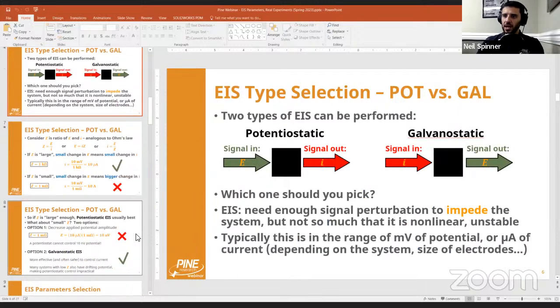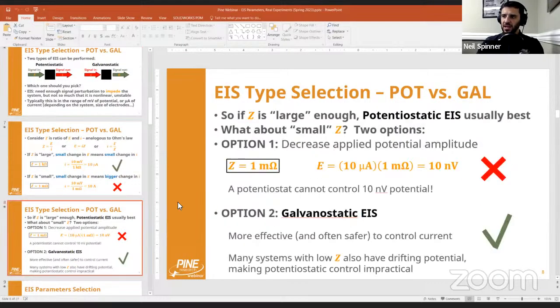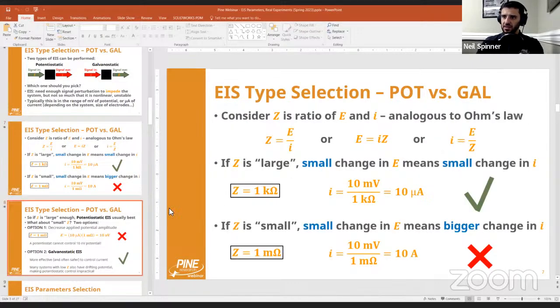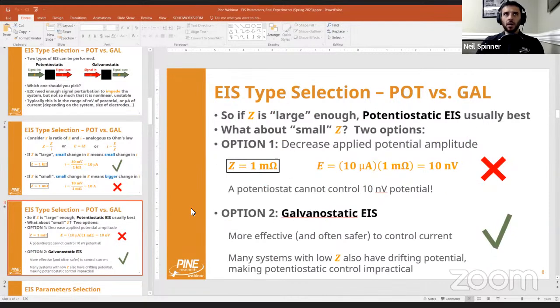So practically, what a lot of times it boils down to is, I'll try to make this more practical rather than the math of whatever the impedance is. Practically, low impedance systems, you're going to do galvanostatic. Mid to high, you're going to do potentiostatic. There is this odd phenomenon that I've found that galvanostatic is both more dangerous, but sometimes much better control if you can get away with it.